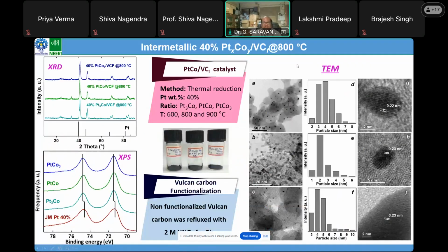This is part of the CSIR hydrogen mission project that we have developed. We have targeted the intermetallic phase of platinum and cobalt. Here we have increased the platinum loading up to 40%, which is required to take care of the sluggish oxygen reduction reaction. And we have ensured the targeted phase. We performed XPS to see whether the electronic structure is changing or not when compared to commercial platinum. We selected the commercial Johnson-Matthey platinum catalyst as the benchmark for performance.